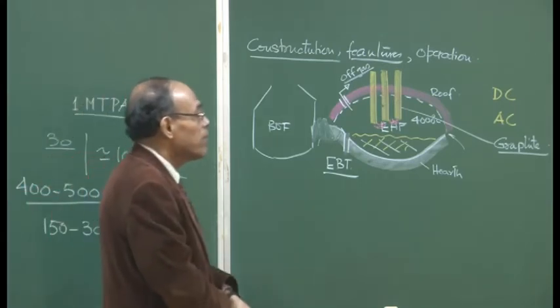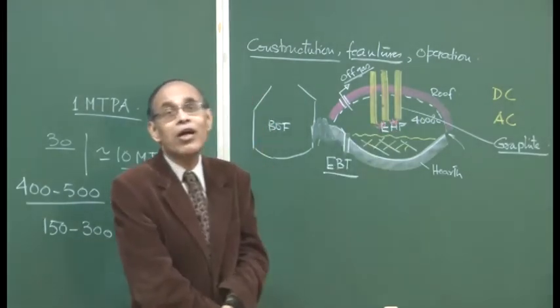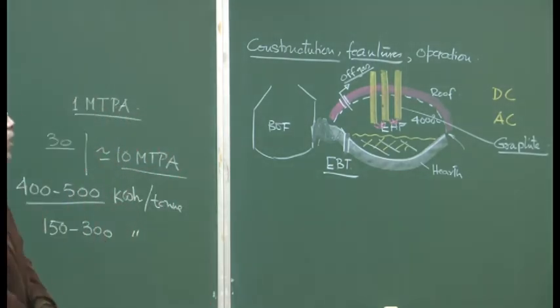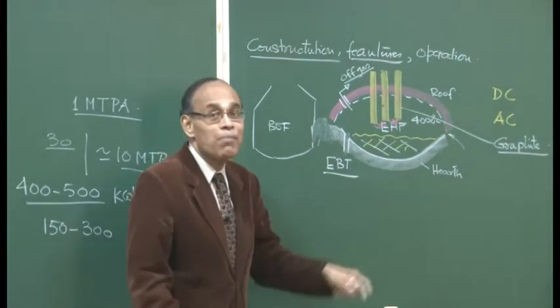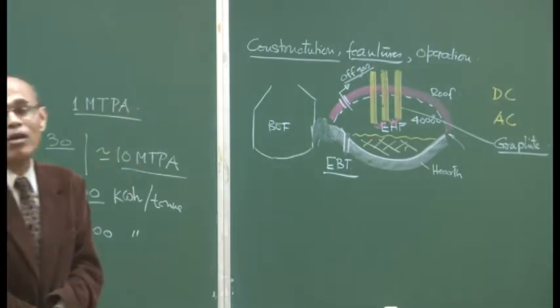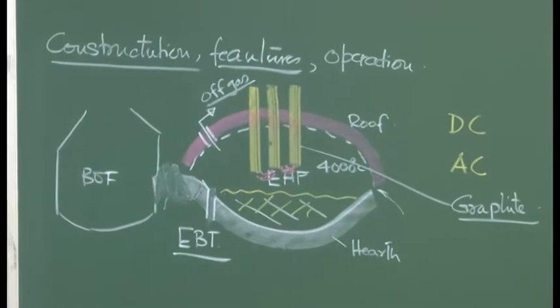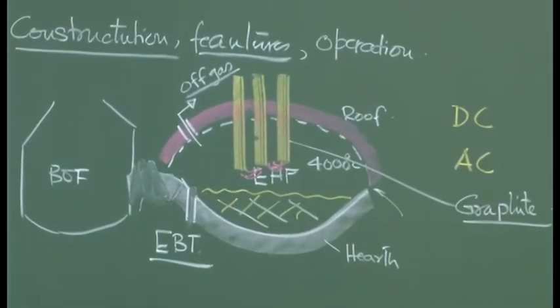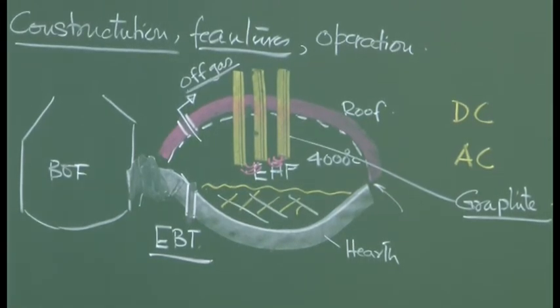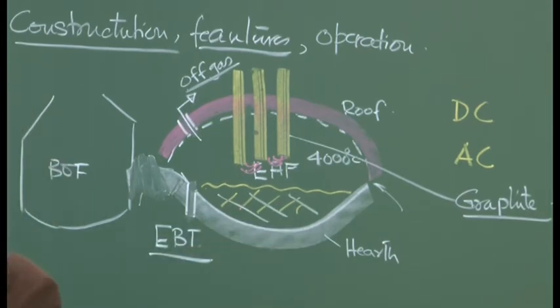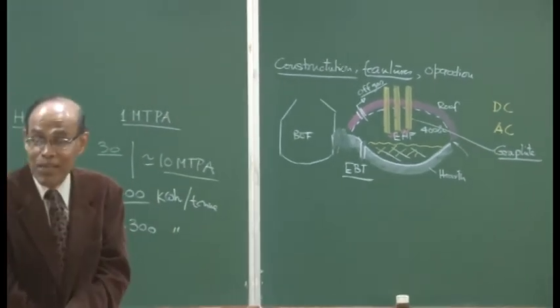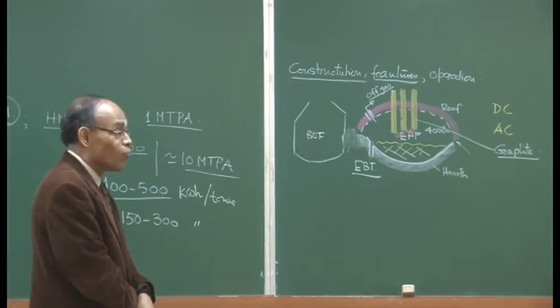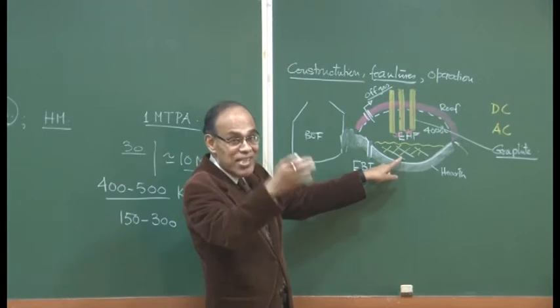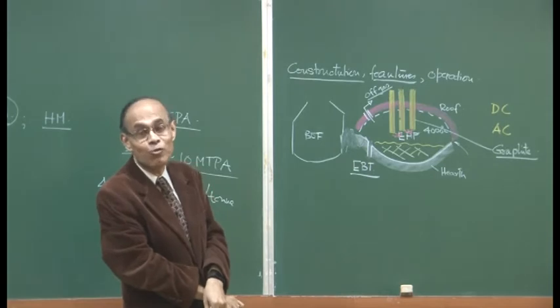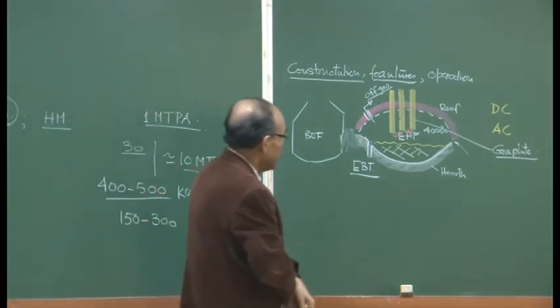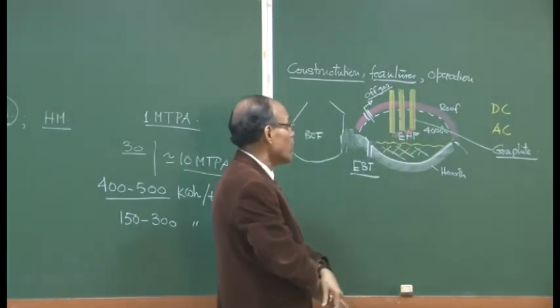They are water cooled, and because they are water cooled, the atmosphere contains really quite a bit of moisture at any point of time, and therefore, the electric arc furnace is still susceptible to more hydrogen content. In BOF steel making you can get 1 to 2 ppm of hydrogen, while in arc furnace steel making getting 5 to 7 ppm hydrogen is quite frequent. Okay? And therefore, this is a big problem, and as I have indicated during one of the earlier lectures, for critical applications hydrogen is not allowed beyond 1 to 1.2 ppm, and therefore, if the steel contains 5 ppm hydrogen, there is a necessity to have a subsequent dissolved hydrogen removal step. So, that we must remember, and the principal source of hydrogen is due to the water cooling of the electrodes.